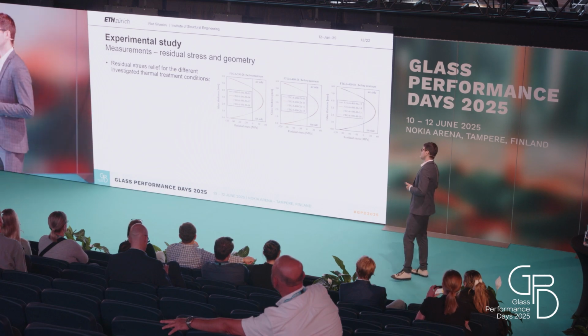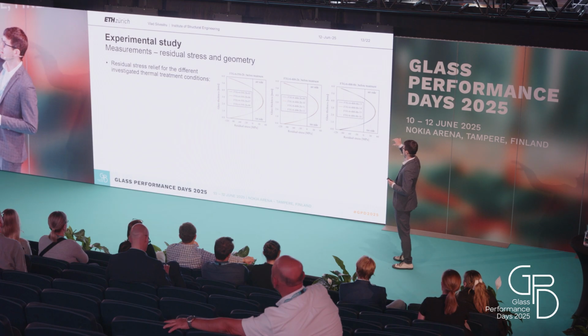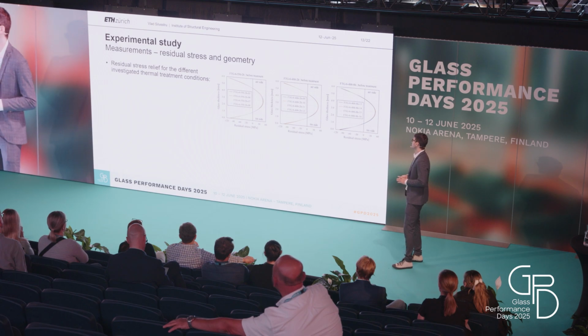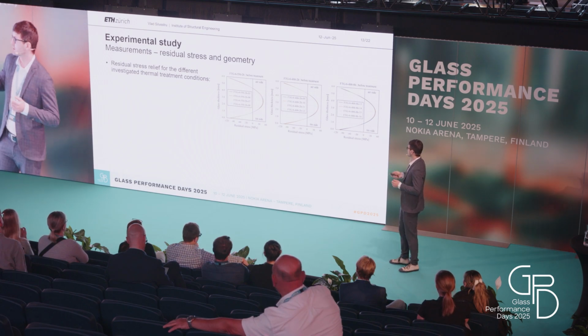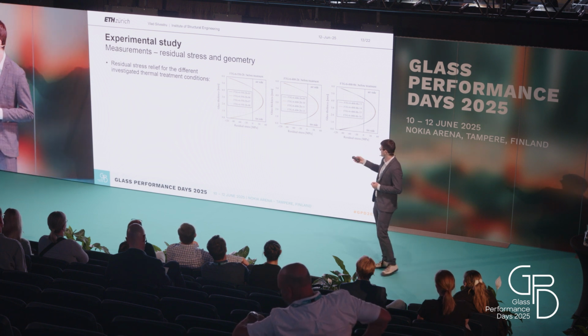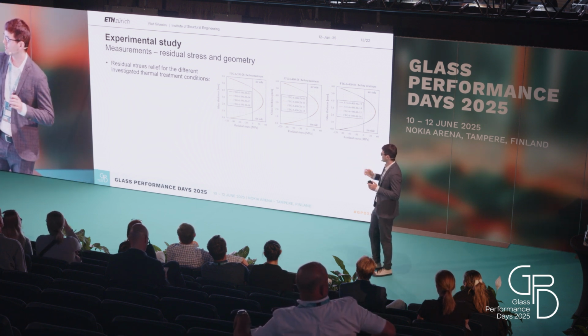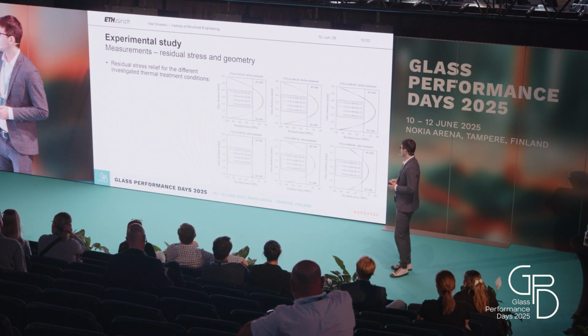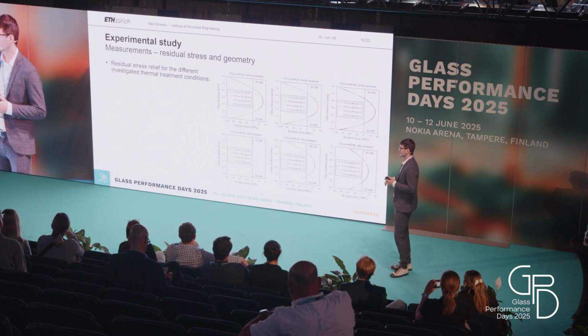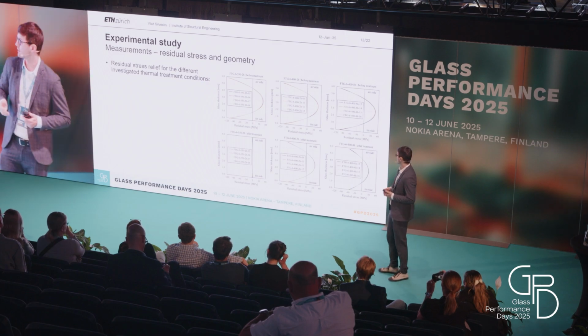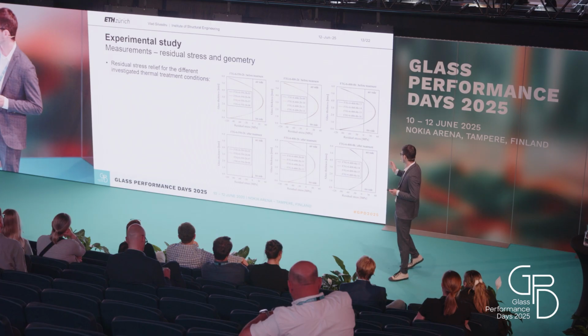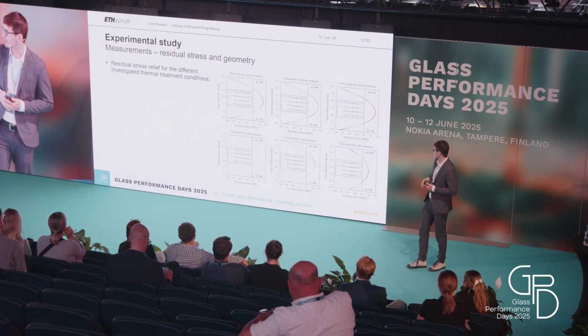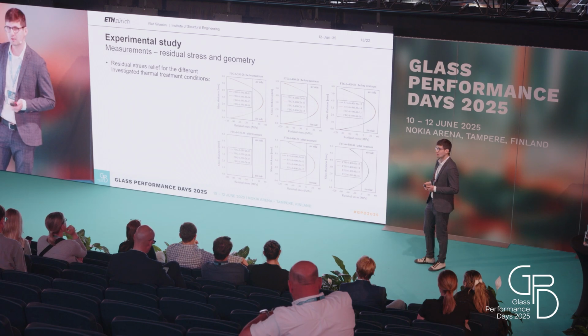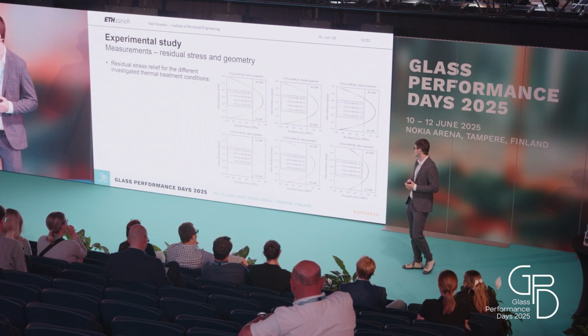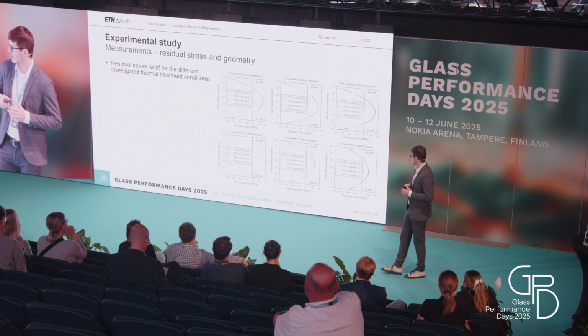Here I would like to show the residual stress distribution. These are for the 3 series at 550 degrees, and so the one at 550 degrees and the 2 at 400 degrees. Before the treatment, we see that we had quite high residual stresses, compressive stresses at the surface, around minus 110 megapascal. After treatment at 550 degrees, we got completely rid of the residual stresses. With 400 degrees, there was a reduction. The reduction was higher with the longer holding time, but we can still see that we have quite high residual stresses.